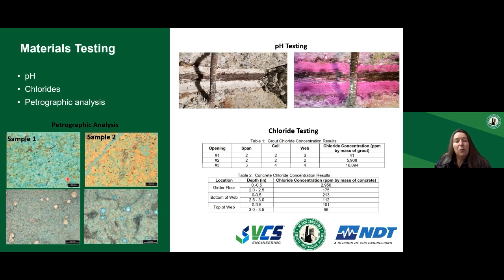As you can see, sample number 1 has a much more intense blue color. The blue here is coming from the epoxy that is used to stabilize the grout samples for a thin section. And the prevalence of the blue in sample 1 indicates that it has a higher water to cement ratio because more epoxy was able to penetrate into the capillary pores in the grout. So the higher the capillary porosity, the higher the water to cement ratio.